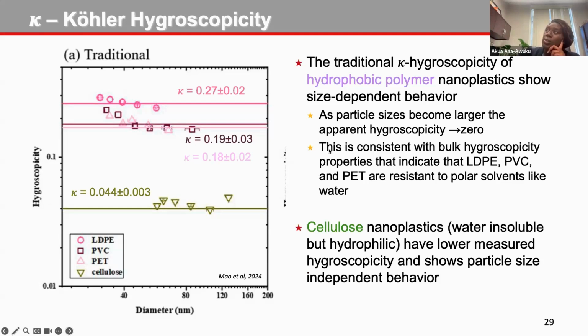When we look at cellulose, cellulose actually has a lower hygroscopicity than the hydrophobic polymers. That is, it likes water less than some of these nanoplastics that were leached into solution, which was very odd at the time. But we'll get down to some suggestions as to why that is.